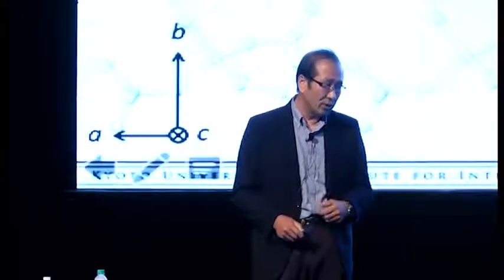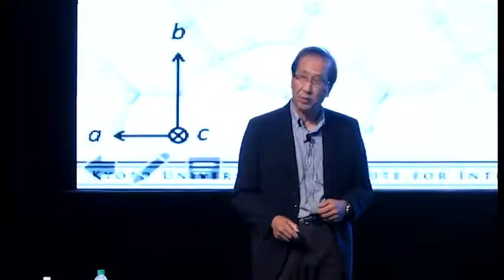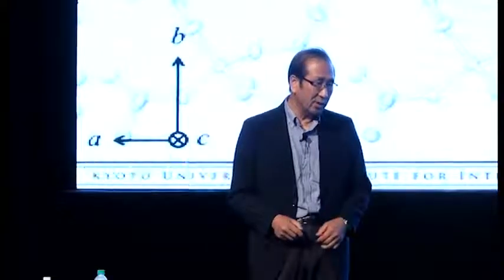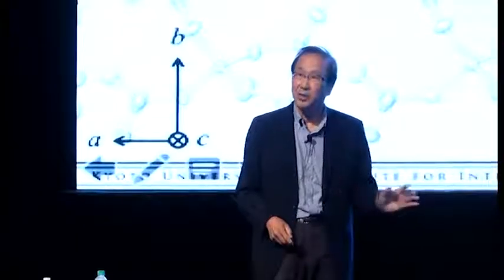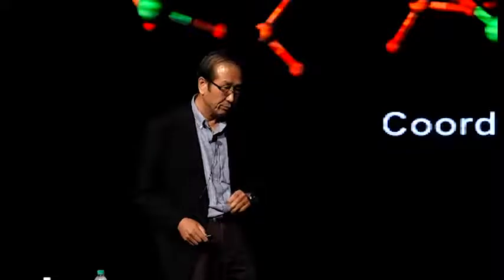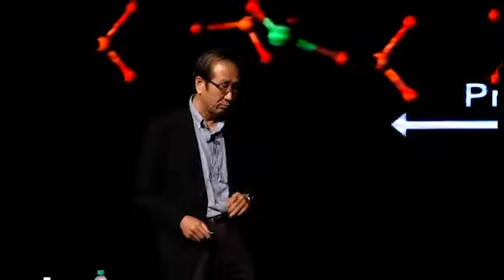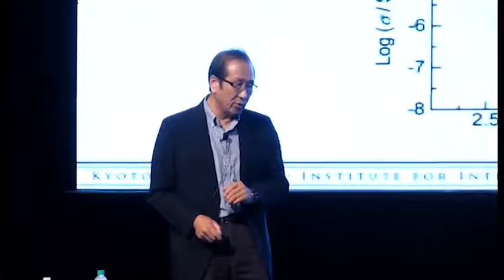Okay? We determined the crystal structure at minus 50 degrees Celsius, so we exactly determined the positions of the atoms of the imidazole cations. But at 80 degrees Celsius, dynamic disorder happens. It's very difficult to see. That means the imidazole rotates very fast. Okay? Like this. So the conductivity increases with the increase of temperature. This is very good news.